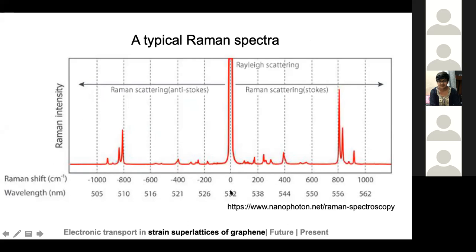So what a typical Raman spectrum looks like, you'll have a very sharp peak at 532 nanometers, which was the incident laser. This also has the Rayleigh scattering component. And then you'll see other intensity peaks show up elsewhere at different wavelengths. Raman shift is calculated as the difference between the wave numbers of these peaks. So what is the shift of these additional peaks which show up? That is characteristic of the crystalline structure and the components of your system. So that gives you a lot of information about how your structure looks, what are the elements in there,